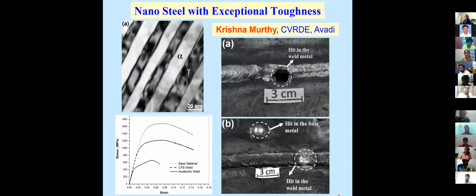One more thing, we can make a material very tough by making it nano. For example, in your own Chennai, in Avadi, there is something called CVRDE, where they make armor plates for tanks. If you have ever seen a tank like the Arjun tank in Google or so, you would see that in front of it there are steel plates, which prevent any bullet from hitting the tank. But the problem is they were using steel, and whenever you weld steel, people found that the welded joint is so weak that if you fire a bullet, it pierces through the welded joint. So it does not have enough toughness. It does not absorb energy. They need something which will absorb the energy of an incoming bullet.